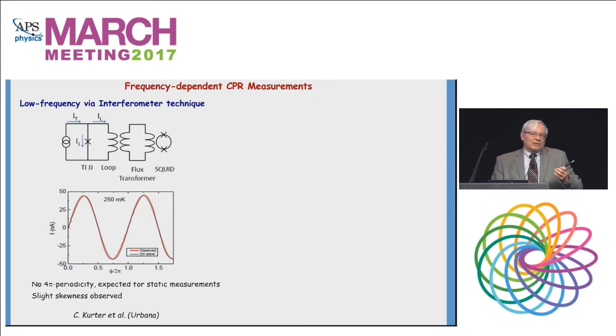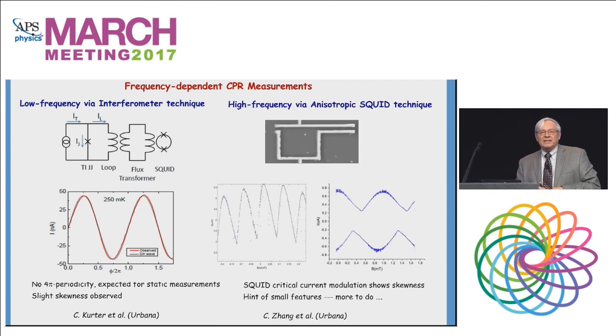Okay, so what we're doing now is to try to do current phase relation measurements. If you do it slow with the interferometer technique, you indeed do not see anything. You don't see any evidence for 4 pi periodicity. We do see some skewness. This is very slow because you expect a lot of parity transitions. If you do it fast with, say, the anisotropic SQUID, we would expect to see something. In this case, we see distinctly skewed current phase relation. And you can make up your own mind if these little kinks here mean anything. This data was sent to me last night by my graduate student, so we haven't had time to analyze it.